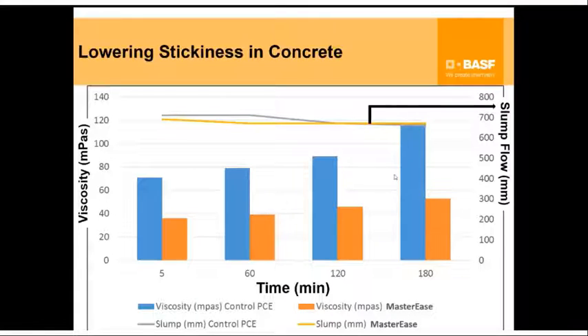In order to do this experiment, it's very critical that you maintain the workability similarly for both the experiments. Because if the workability is different, it automatically changes the viscosity properties, and then the comparisons may not be valid. So as you can see, with the yellow line and the gray line for these two experiments, one with a normal control PCE and one with a new viscosity reduction kind of a product, you can see that the workability retention from 5 minutes to 180 minutes were held as constant in both cases.